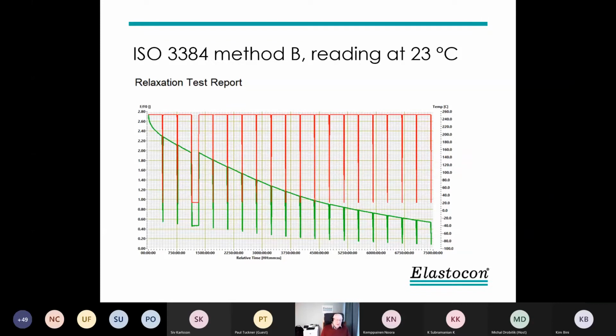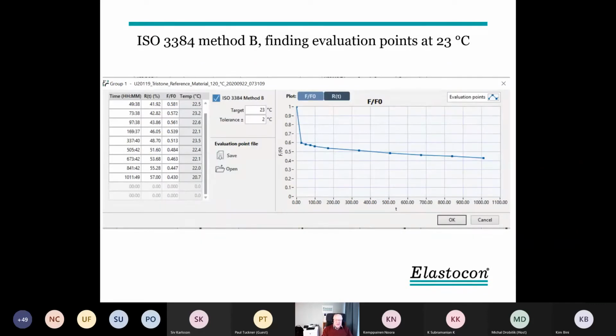And the interesting thing is, in fact, the value of the peaks, say the downward peaks, so they change with time. And that has been a little job to evaluate originally, but now we have improved our software, so it's more easy to do it. We have a function where we let the software find the 23 Celsius temperatures, and then we can get the plot from the times when we want to measure 23 degrees. So here we have, I think, 24 hours, 72, 96, 168, and so on.